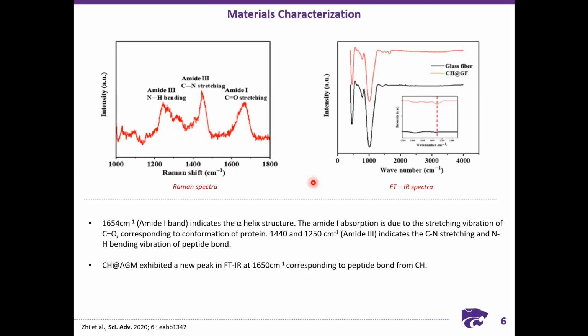So also from the FTIR, from the difference between the glass fiber and the CH at glass fiber interlayer, we can see there is a new peak at around 1650 wave number, which corresponds to the peptide bond from CH. All other peaks correspond to the silica present in the AGM. So these Raman spectra and FTIR, and also the EDAX mapping from the previous slide, confirm that the collagen hydrolysate has indeed been coated on the surface of AGM.